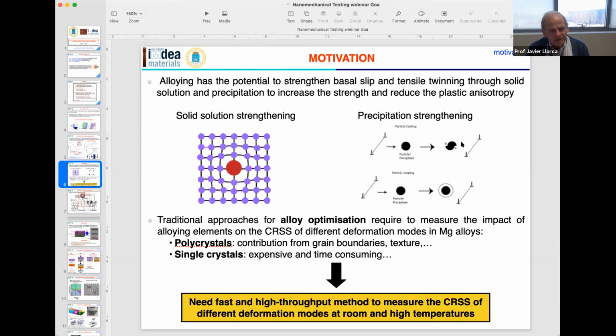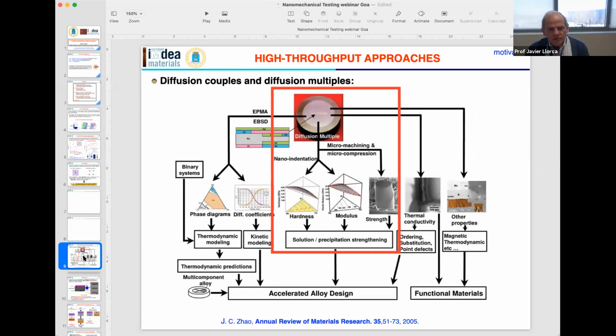But if you really want to measure the impact of alloying elements on the critical resolved shear stress, then you have different strategies. First of all, you can manufacture the material and do tests in polycrystals. But when you carry out tests in polycrystals, it's very difficult to differentiate the contribution of the alloying element from other contributions, for instance from the grain boundaries or from the texture. So the results are not very precise. Another possibility is to cast a single crystal and do experiments on single crystals in a given orientation. But of course, if you want to do that for different alloy compositions, this is very expensive and time consuming. So there is a need for fast, high throughput methods to measure the critical resolved shear stress of different deformation modes at room and high temperature. And this is basically the main motivation of this talk. So what do we do in this case, or what is the best idea? Well, the best idea is to use what are called high throughput approaches.